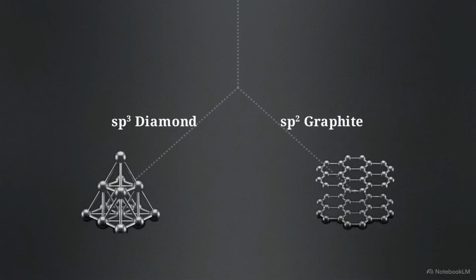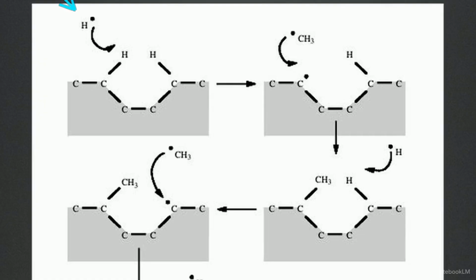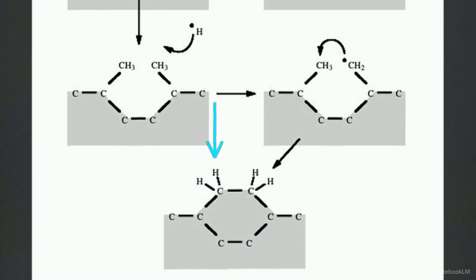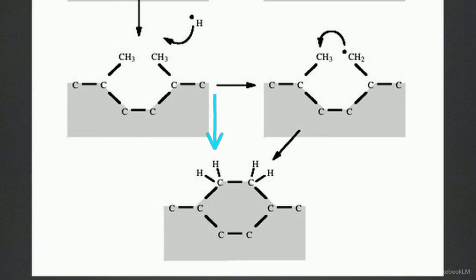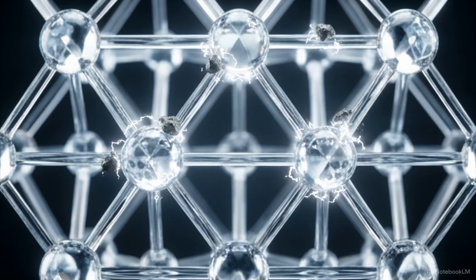As those carbon atoms rain down, they face a structural choice. They can form ultra-hard diamond, or they can form soft, flaky graphite. Atomic hydrogen manages growth. It acts as a selective agent, removing graphitic carbon bonds while leaving the diamond lattice undisturbed, allowing methyl radicals to attach. Finally, hydrogen caps the surface, locking the carbon into a rigid sp3 structure and preventing graphite formation. Hydrogen effectively carves away structural errors in real time, ensuring that only the diamond structure survives and grows.